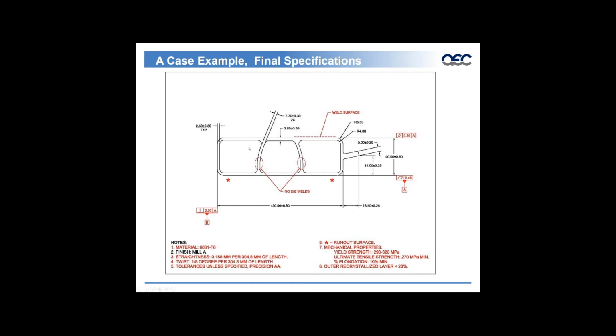Again, a 6061 alloy with these mechanical properties requires a full water wall quench. So we also apply a flatness spec across the bottom for any distortion, a parallelism represented here, and a perpendicularity to hold the squareness of this extrusion as it goes through the quench process, the full water wall quench.